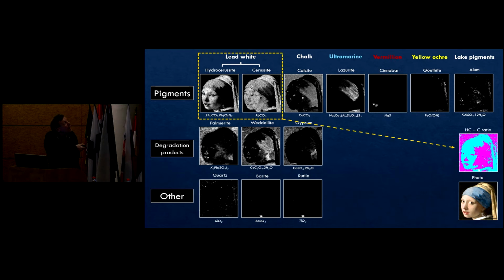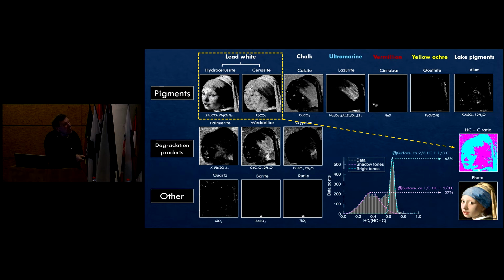And again, if we look at this hydrocerussite-cerussite ratio, we see actually two categories. We have the light parts of the portrait, and the darker ones, the shadows. And this prompted us, so you can figure this out, there is a big difference between these two. But not only that, if we use this scanning XRD, we also get a sense of where below the surface the components are. Because there is a small shift in the diffraction pattern when things are deeper than the surface.